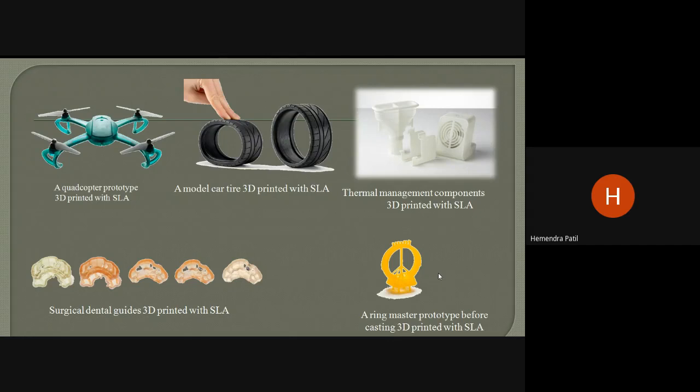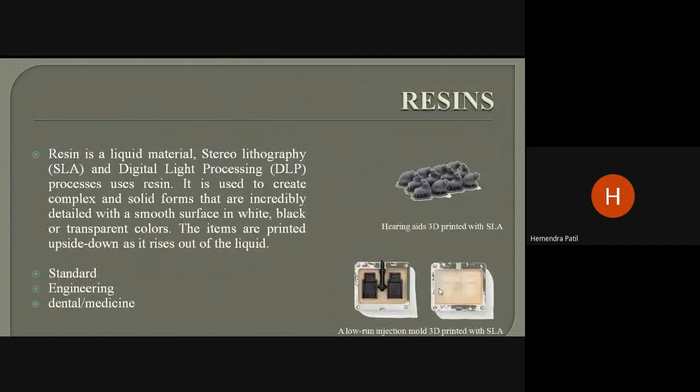There are some heat resistant resins also, which are used for molding. Here I have shown one product of heat resistant resins. Heat resistant resins are ideal for applications that require high thermal stability and operate at high temperature. These resins have a heat deflection temperature between 200 to 300 degrees Celsius and are ideal for manufacturing heat resistant fixtures, mold prototypes, hot air and fluid flow equipment, and casting and thermoforming tools.